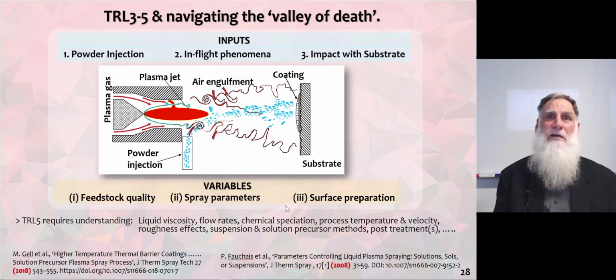So let us go back to this slide that addresses the processing of coatings. We have inputs: powder injection, in-flight behaviour, impact with the substrate, as indicated by this picture. And we have variables: feedstock quality, spray parameters, and surface preparation. To get to technical readiness level 5, we need to understand these effects for liquid techniques. The liquid viscosity, flow rates, chemical speciation, process temperature and velocity effects, roughness effects, suspension versus solution methods, post-treatments, and many other factors. These factors are pointed out by Gell et al. in 2018, as well as by Fauchais in a review paper in 2008.